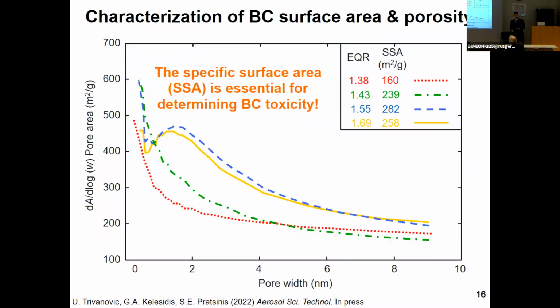It was not possible before because to do reliable nitrogen absorption measurements, you need at least a few milligrams, 20 to 30 milligrams, to do such measurements at the lab. And this, of course, you cannot obtain easily from an aircraft engine. So here we are able to obtain enough aircraft-like black carbon, and that way characterize its specific surface area and also its pore size distribution that is important also for its climate effects, for example, to see how clouds are forming around these nanoparticles in the atmosphere. And again, this is quite important because the specific surface area determines the toxicity of such black carbon emissions.